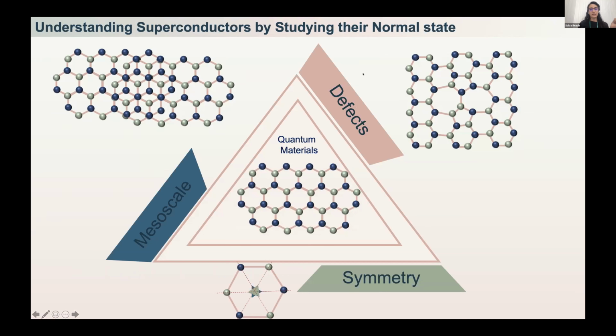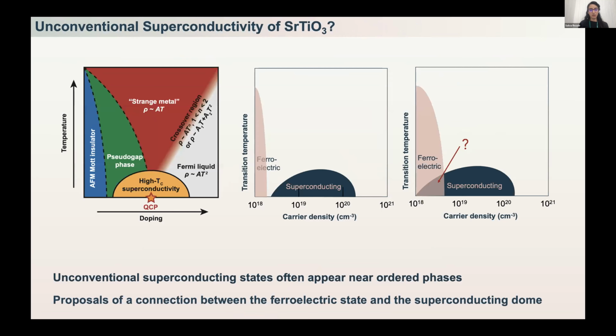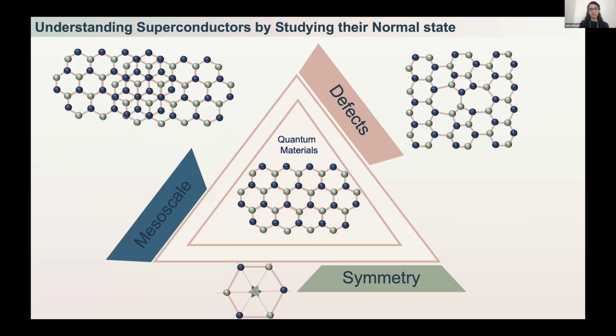For example, we have a great tool to investigate the defects in these materials. Oftentimes, based on the nature of superconductivity, these materials can be fault tolerant or not fault tolerant, and they can be sensitive to defects like magnetic defects. We also have a great tool to investigate the local structure in these materials. Oftentimes these local structures are hidden from global measurements, but we can investigate them and understand whether they participate in superconductivity. And we can also use this technique to investigate symmetry, which will become particularly important in understanding topological superconductors.